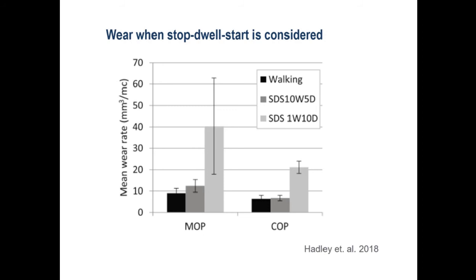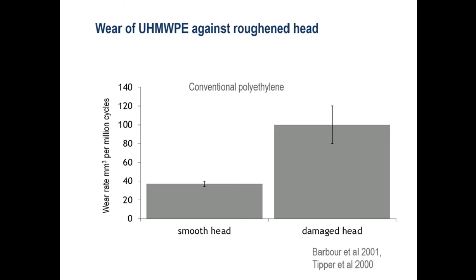you can actually increase the wear rate of a metal on polyethylene or a ceramic on polyethylene bearing compared to testing it only under a standard walking cycle. And you can see that the wear of polyethylene increases when articulating against a damaged head or a roughened head compared to a smooth head.